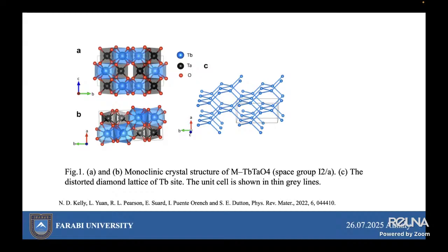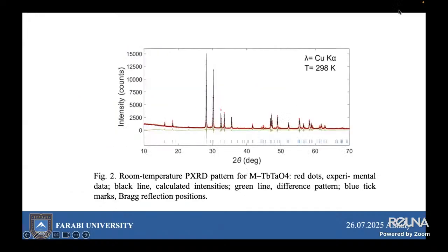And the Rietveld refinement of the room temperature PXRD of terbium tantalate is shown in the next picture. Here, the red dots are experimental data, the black line is the calculated intensities, the green line is the difference pattern, and the blue tick marks are Bragg reflection positions.